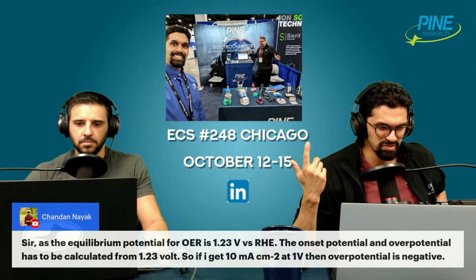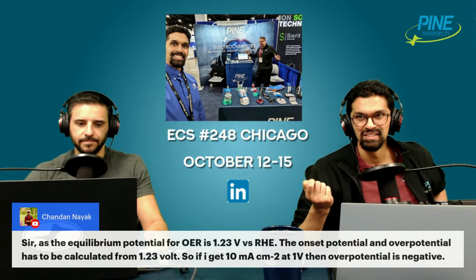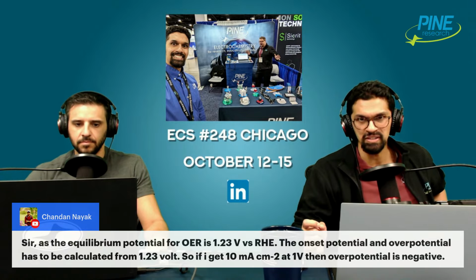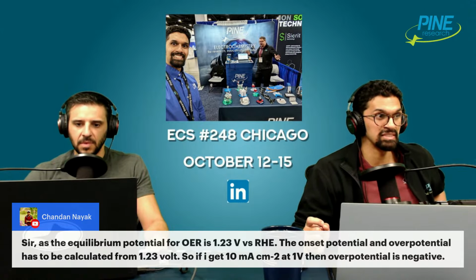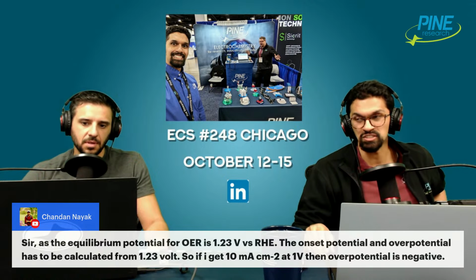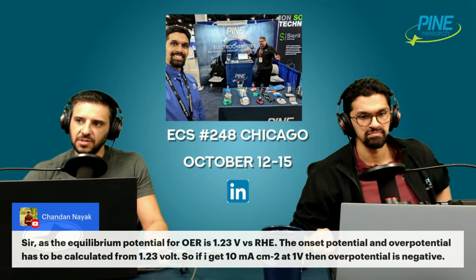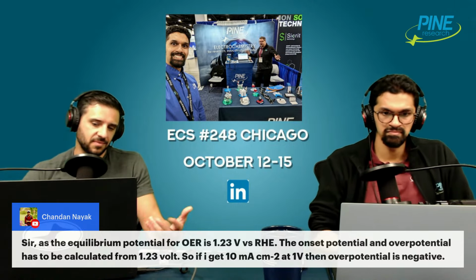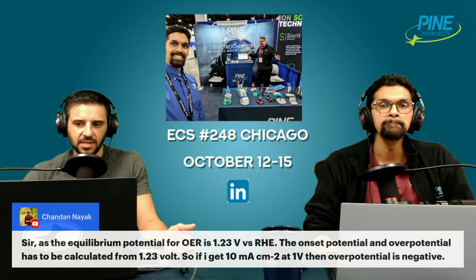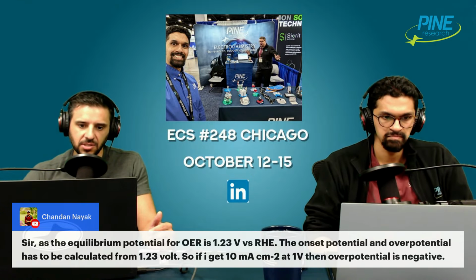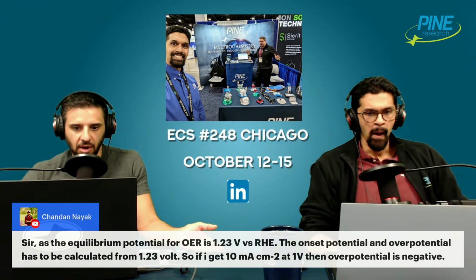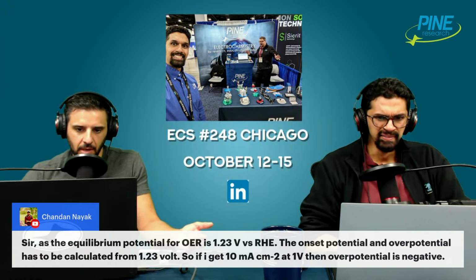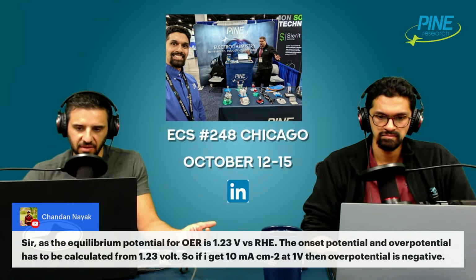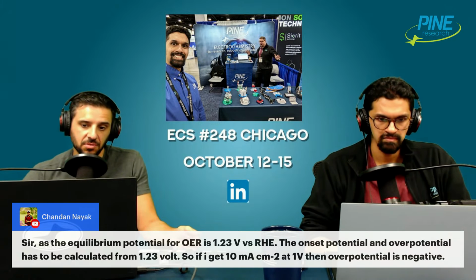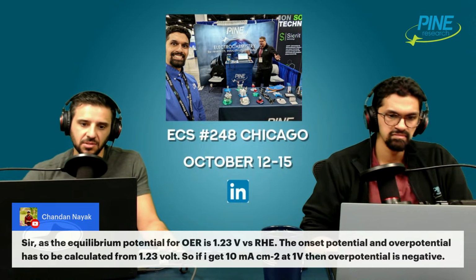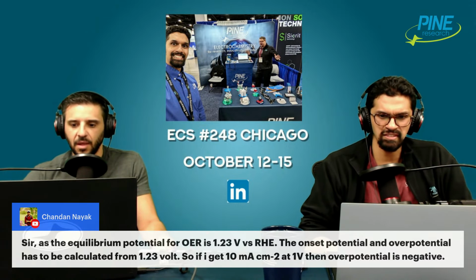And that brings up the other point. You should be scanning very slowly for an LSV experiment. Also check your pH. Standard potentials technically can shift. By the Nernst equation, it's about minus 60 millivolts per pH unit, which means if you go up in pH, the potential will shift negatively. So in alkaline systems, if you're talking about, let's say, 240 millivolts, that's 4 pH units. Did you change by 4 pH units? That could explain the shifted potential. Just saying.